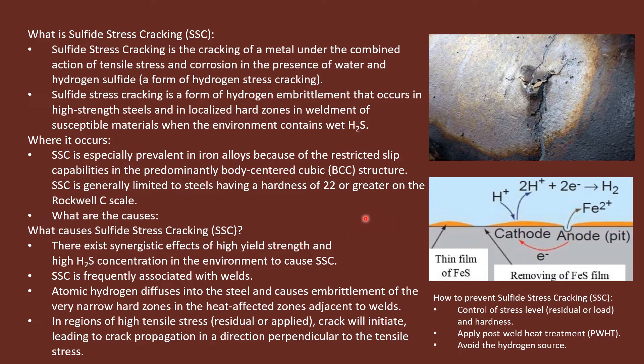To prevent sulfide stress cracking, we can control the stress level — residual stresses can be removed — and we can control the hardness. Once we control these two factors, stress level and hardness, there are less chances of this kind of cracking. If we apply post weld heat treatment (PWHT), this will further reduce residual stresses. We can also avoid the hydrogen source by keeping our material away from hydrogen sources, which results in lesser hydrogen embrittlement.